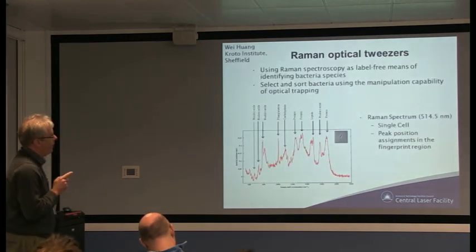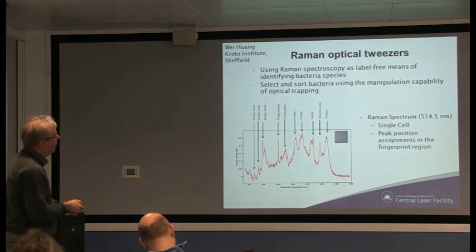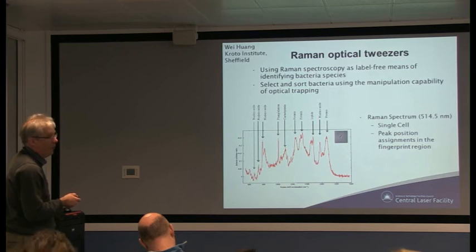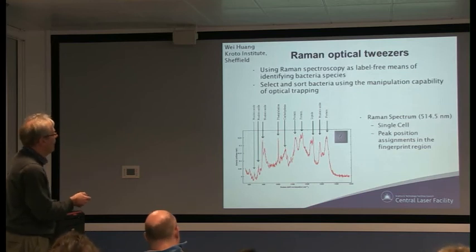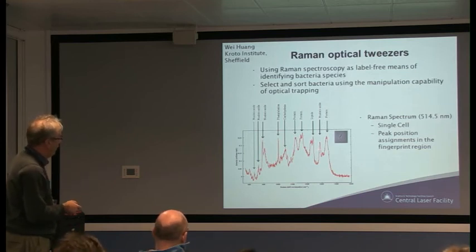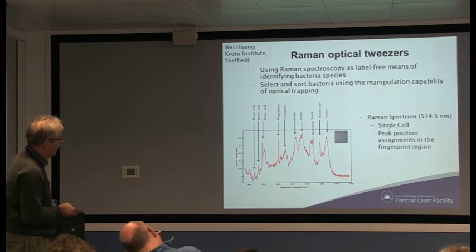For the application here, I'm actually highlighting some of the work we do, combining the optical trapping with Raman spectroscopy. So basically we're looking at how the laser light interacts with the molecules. It's a vibrational spectroscopy technique. You'll often get a shift in the wavelength during the interaction, and the intensity of the shift is related to how the molecule's vibrating or rotating. So this is a Raman spectra of an optically trapped bacteria species.